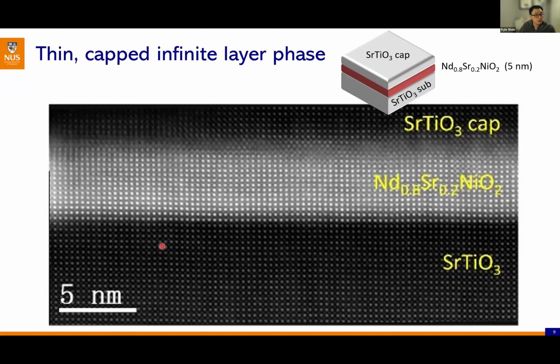So did you also look at the thickness dependence? No, all of our samples were basically the same thickness, with the same capping layer thickness as well. We just used different reducing conditions. If you reduce it more lightly, you get almost all 337 or 338. And if you reduce it fully, this signal completely disappears. And the thickness, remind me again? These are 20 unit cells.